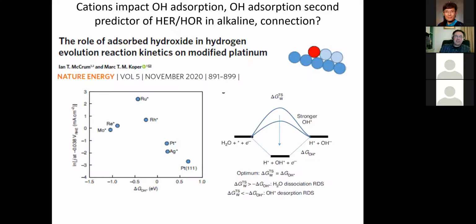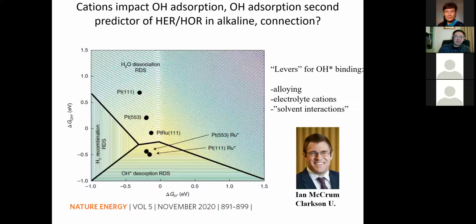And then they use this to say, well, that's true under some pHs and some conditions. So we really still need these two descriptors, hydrogen adsorption and hydroxide adsorption, in order to dictate what would be the rate determining step. And with that, then we get a volcano. So I hope you see coming out of the screen here, this height is the best catalysts. The highest rate catalysts are at the top of this two-dimensional volcano now with two descriptors.